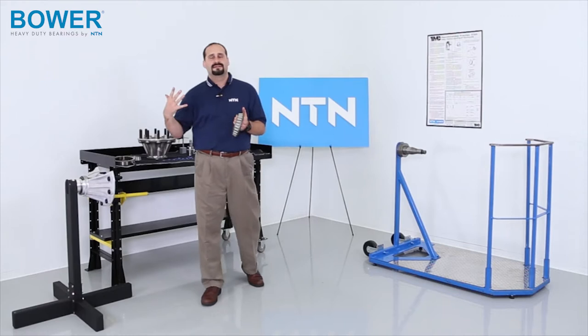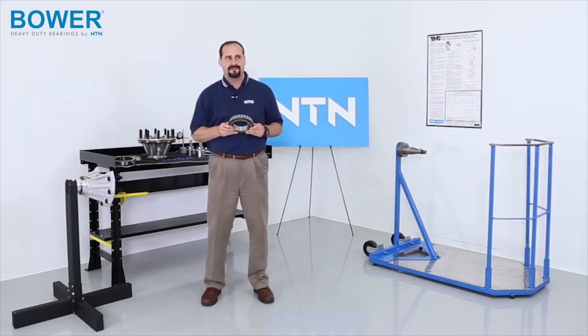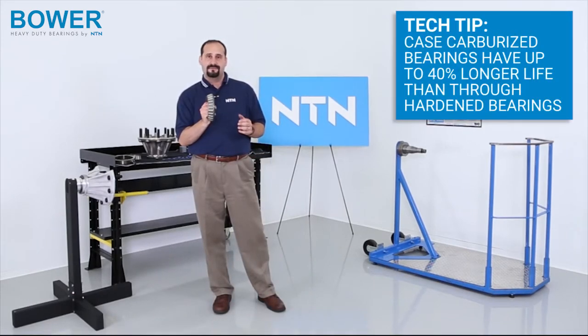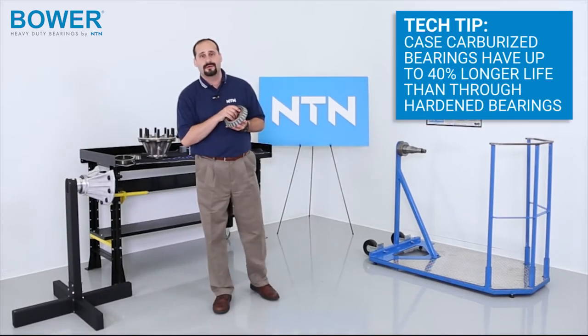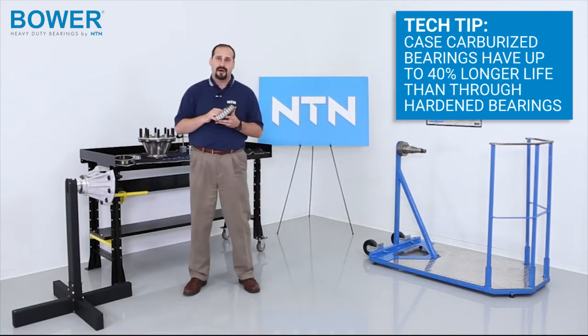This is in comparison to through-hardened taper that's common from overseas suppliers where it's hardened to the same degree all the way through. So, your case carburized material gets you, roughly speaking, 40% longer life than a through-hardened part. And it also gives you much more shock resistance.